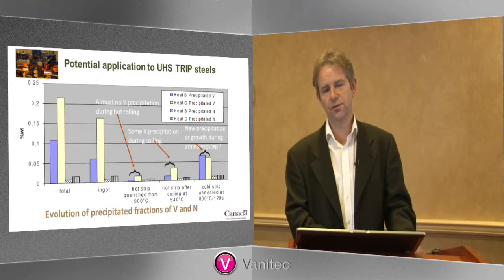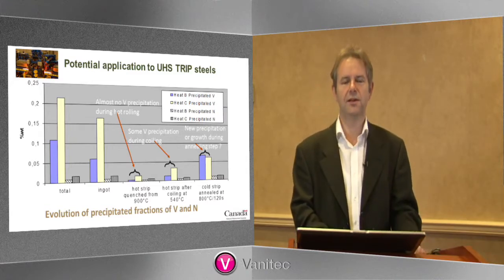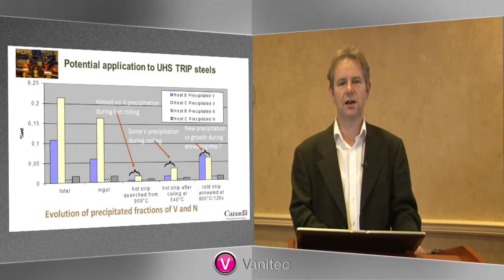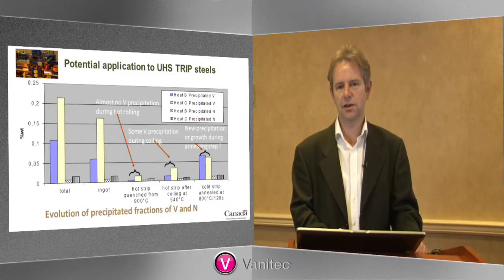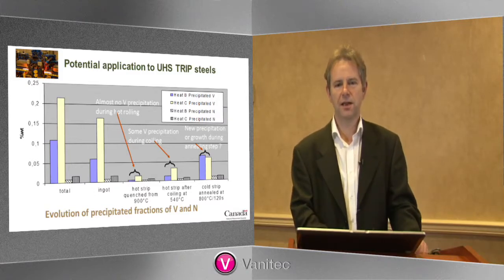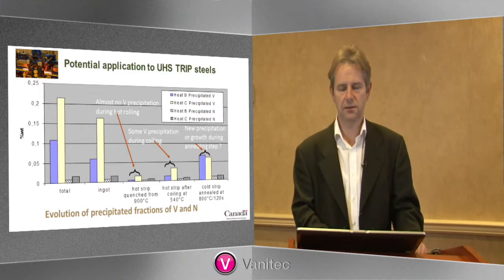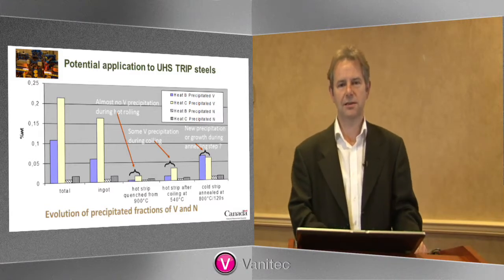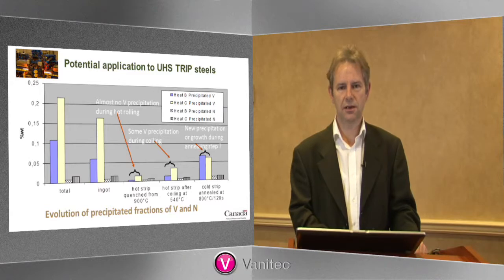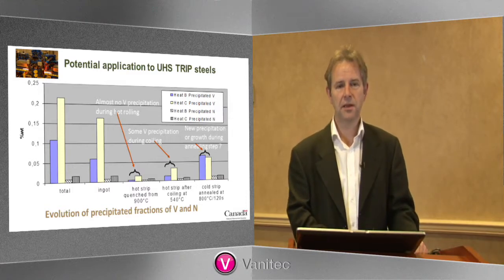Then obviously you don't do this in industrial practice, because you end up with martensite and you can't do anything more with it. What you'll do is you'll do a controlled cooling and then a coiling. We chose to coil at 540 degrees C here, which is quite accessible for most lines. And again, you can see that we did get some increase in the vanadium precipitation, but not very much. So we've managed to keep most of the vanadium from here in solid solution up to here. Then we did cold rolling, and we did continuous annealing after the cold rolling. And we looked at the vanadium precipitation after that step. And what we can see is that we actually increased significantly the amount of precipitated vanadium in the steel, up to a point where we actually had more than we had precipitated in the original ingot.